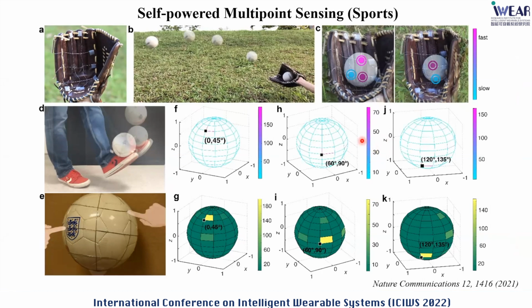Because during sport, we see a lot of sudden physical impact. And if we have the conventional wearable devices, they're quite easy to be damaged. So when we have those ultra stretchable fibers attached on the surface of a baseball glove, even after this type of high-speed catching, those sensors still survive, and more importantly, they can also monitor, for example, the speed from different points, which can help with the practice. So this is the first short story about how we use those soft materials.